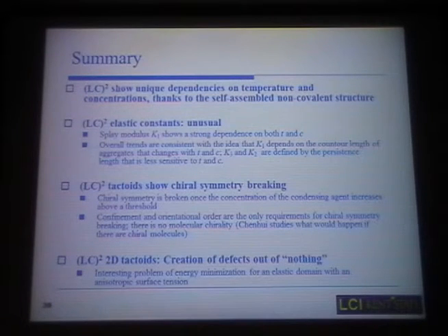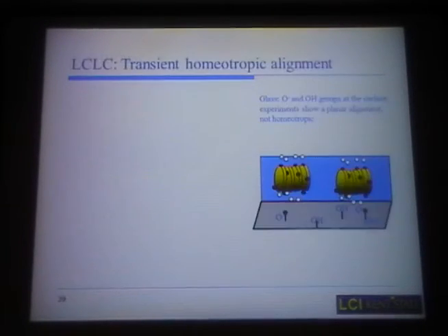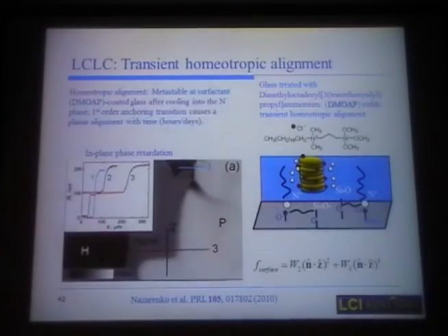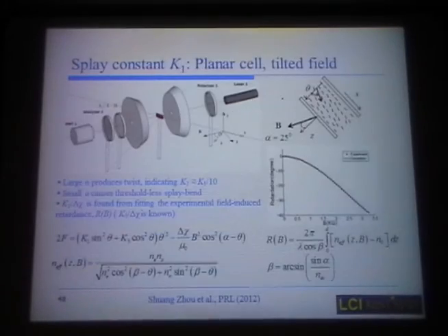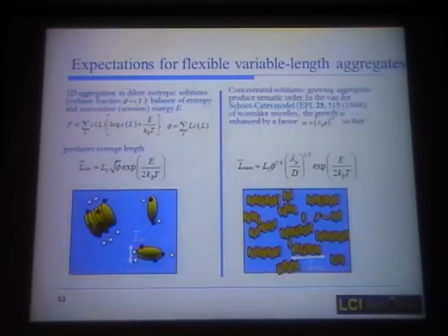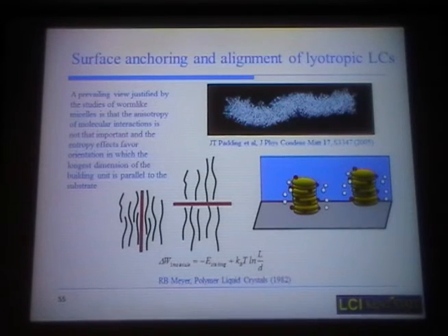Yeah, you've shown that you could align a chromonic in a magnetic field, and you can also do it, I guess, by rubbing. You should also try electric fields to align these kinds of molecules. Yeah, it's an important and very difficult question. You see, the lyotropic liquid crystals are extremely hard to align, and this is the illustration of why. Because when the aggregates are long, the entropy comes into play. To have, for example, a homeotropic alignment, you need to find enough ends of the aggregates to organize this alignment. So we spent a lot of time.